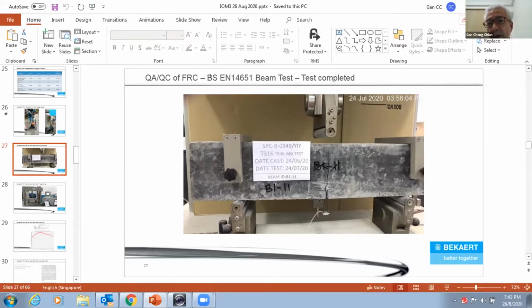But today, because BS EN 14651 is the recognized test method, all beams have to be cut. So if I'm cutting the beam at the center here, then I will just use a 3-point load, and I use a CMOD to check the deformation. So the other test that you mentioned is 2-point load. With 2-point load, I don't check the CMOD. I will use a displacement transducer to check the deflection.